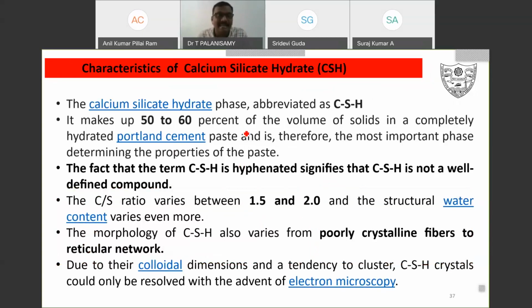The calcium silicate hydrate phases, abbreviated as CSH, make up 50 to 60% of the volume of solids in a completely hydrated Portland cement paste. It is therefore the most important phase determining the properties of the paste.